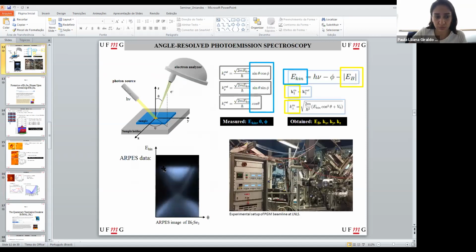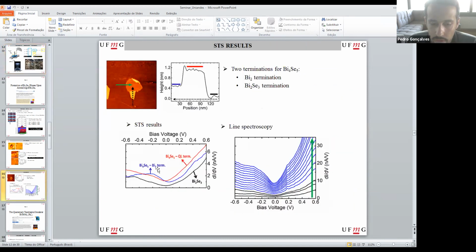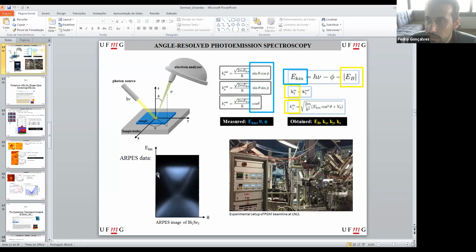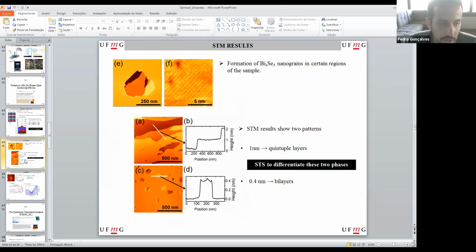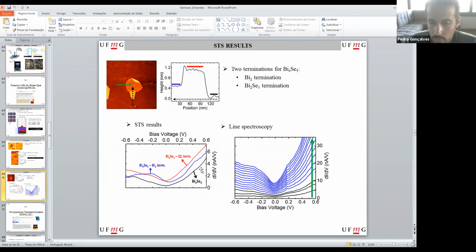Yeah, the thing is, if we have an insulator with a conduction band and a valence band here, we should not have any states here, and in the density of states it will look like a structure like this, because there is a gap, a region where the dI/dV curve is 0. But if you have these states here and this state is linear, we should have a structure like a V here, which is what we're seeing here on the bismuth selenide.